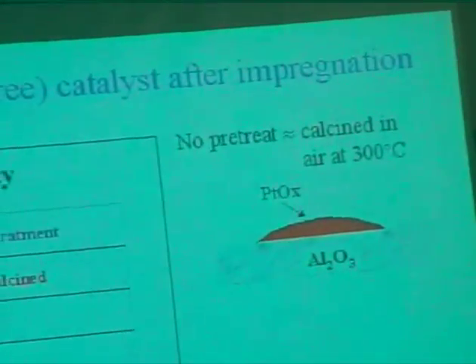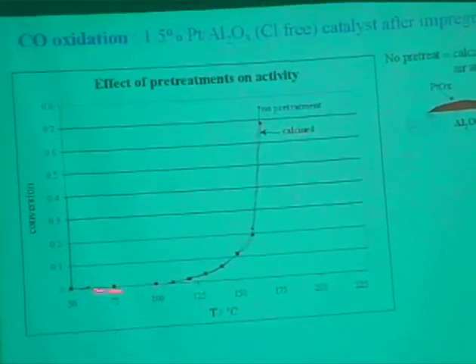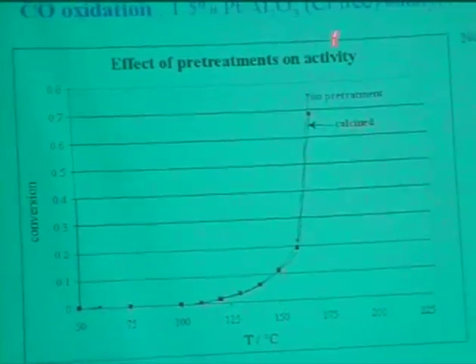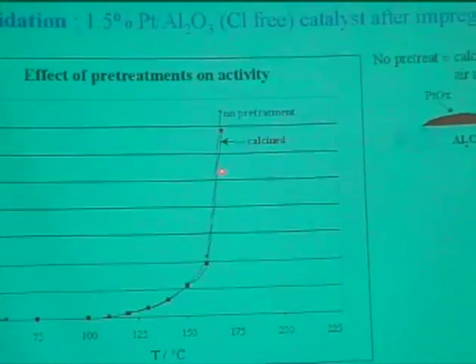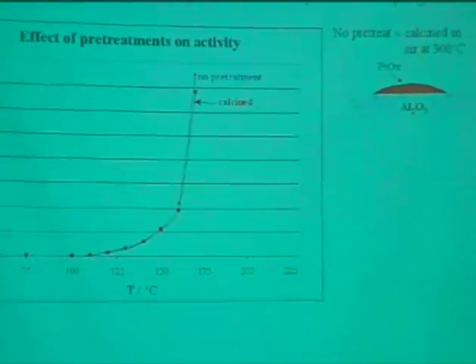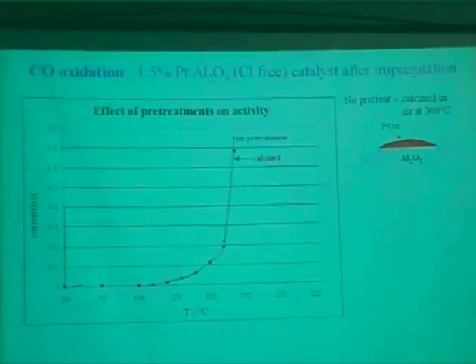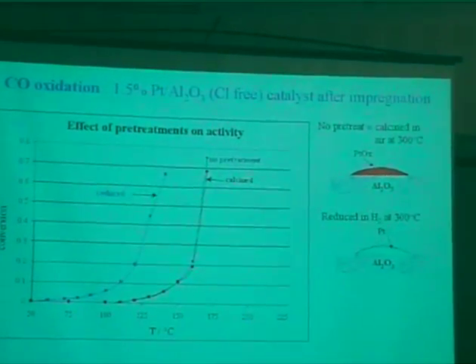And the other thing is that at this higher temperature, apparently there is some sort of an equilibrium coverage of the chlorine that you reach at the higher temperature. Now, we took a catalyst just after preparation, no calcination or anything. So for CO oxidation again, this is a chlorine-free catalyst. This is calcined, and with no pretreatment. In both cases, we got an oxidized surface. Okay, obviously we're calcining the catalyst. We are reacting the reaction itself.